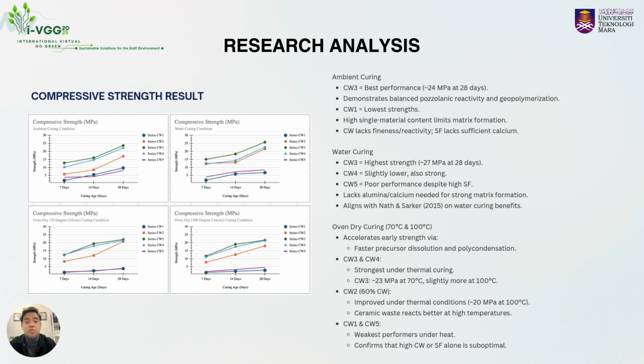The results show that CW3, containing 40% CWP, 40% of SF, and 20% of OPC, consistently performed the best. Under ambient curing, it reached around 24 MPa at 28 days. Under water curing, it rose to 27 MPa. Oven curing accelerated early strength, especially at 70 degrees Celsius. In contrast, mixes with high CWP or high SF alone, like specimens CW1 and CW5, performed poorly due to unbalanced reactivity or lack of matrix